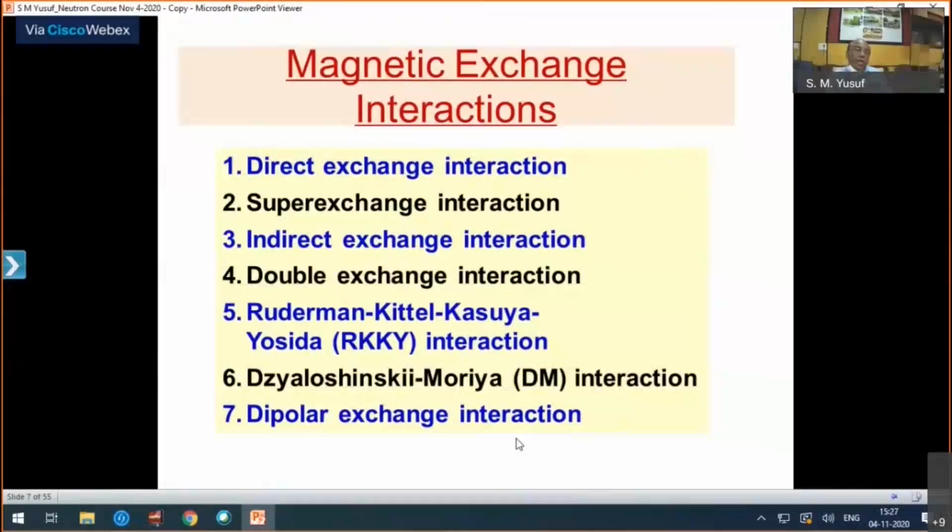So the classical dipole interaction cannot explain this real-life fact that you get a magnetic material where the ordering temperature is very high. Otherwise, all materials should have ordered, if at all, only below 1 Kelvin, because the strength is so weak. In other words, thermal energy would always win above 1 Kelvin.